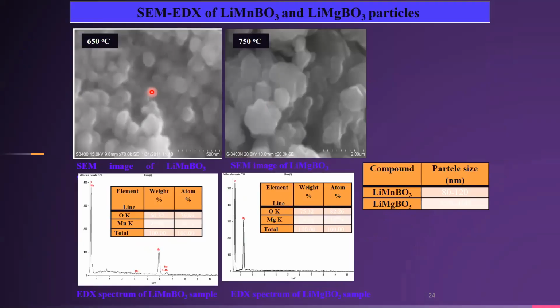And this slide shows the SEM and EDAX of lithium manganese boroxide and lithium magnesium boroxide. The SEM image of lithium manganese boroxide sample at 650 degrees centigrade reflects agglomerated particles, where one particle is separated from another. The agglomerated particles show the formation of irregular spherical shape with sizes ranging from 80 nanometers to 120 nanometers. The SEM micrographs of the lithium magnesium boroxide sample at 750 degrees centigrade reflect agglomerated particles exhibiting sheet-like morphology with particle size ranging from 250 to 400 nanometers.